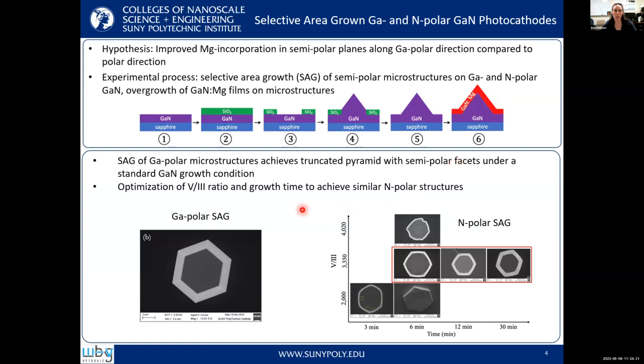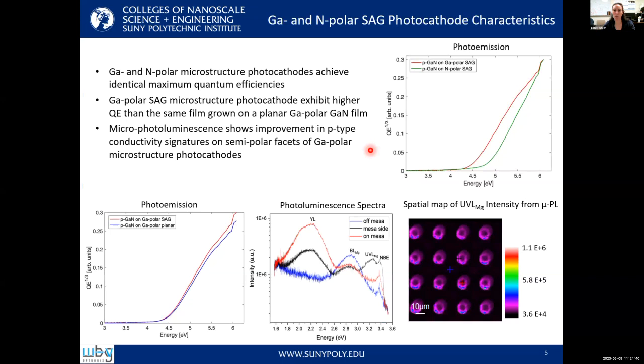So the first result that I presented in my poster was selective area growth of both gallium and nitrogen polar microstructures. And this was the first report of stabilized semipolar facets for nitrogen polar selective area growth microstructures. We then went on to overgrow the magnesium doped film on both the gallium and the nitrogen polar microstructures. And we found that both nitrogen polar and gallium polar microstructures achieved similar quantum efficiencies when measuring their photocathode performance. And when looking at just the gallium polar microstructure compared to a planar counterpart, the gallium polar microstructure showed improved quantum efficiency over the planar film.